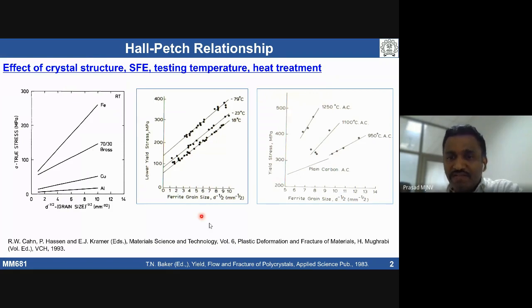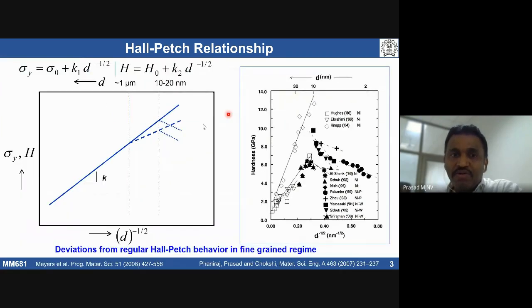Okay, so I think we had enough discussion about these variables which can influence Hall-Petch constants. Then, typically, we do see linear deviation if you make a plot with respect to stress or hardness as a function of d to the power of minus 1 by 2, where d is the grain size. It should supposed to give you a linear line.